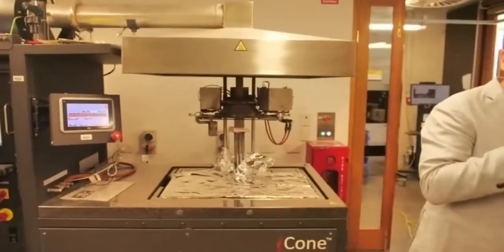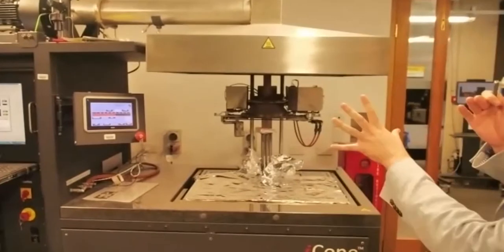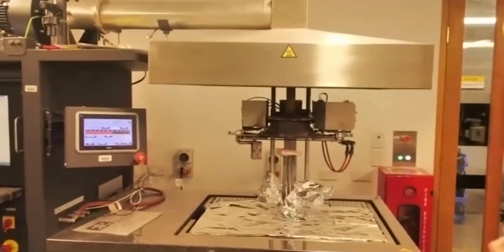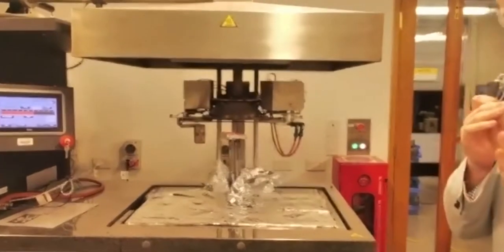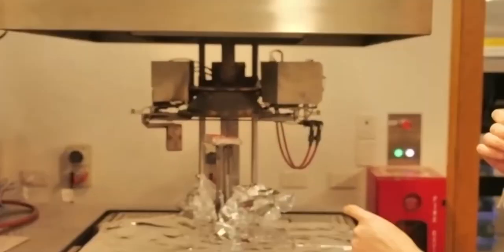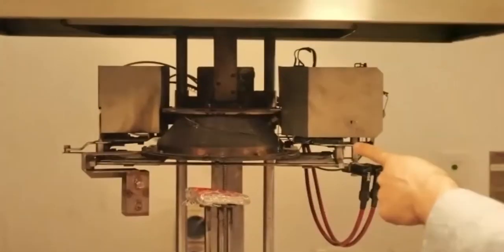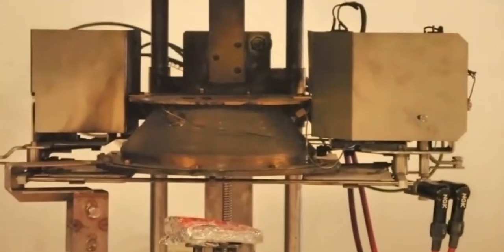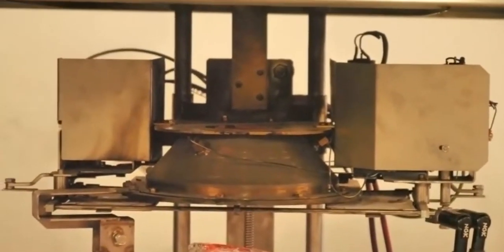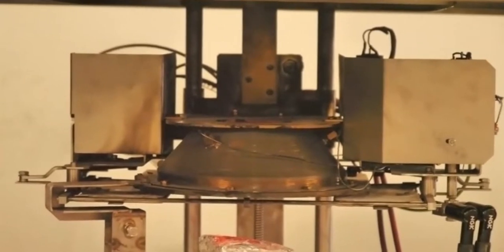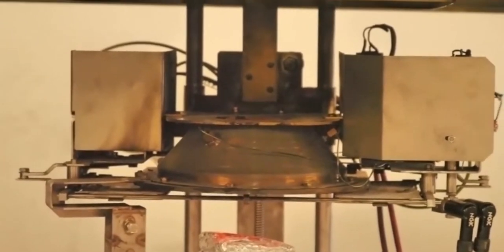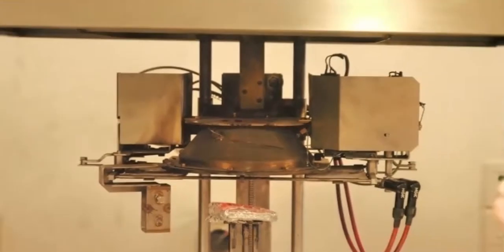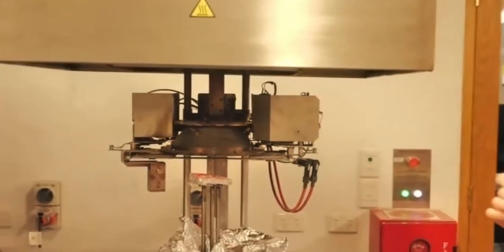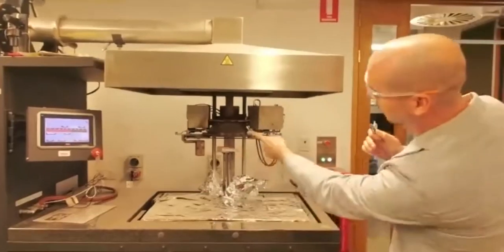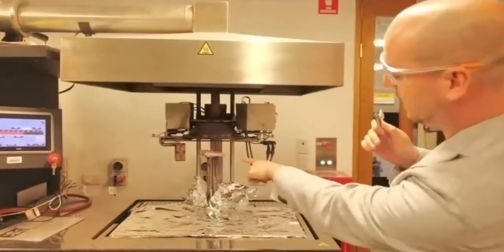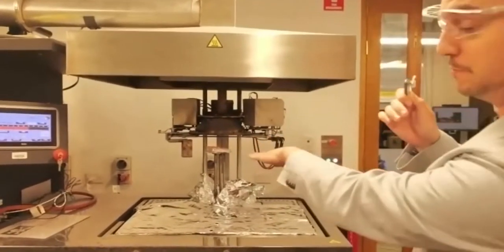Here, what you can see is an apparatus that we call the cone calorimeter. It's called the cone calorimeter because it has a heater that looks like a cone. That heater can go to heat fluxes up to 100 kilowatts per square meter, which is more or less 100 times the radiation that we can receive from the sun on Earth. This system produces a lot of heat at the surface that we will place where you can see this aluminum foil protection.